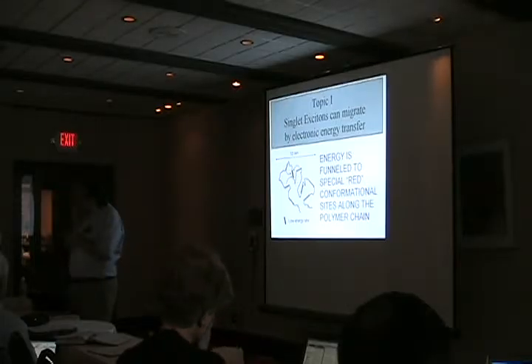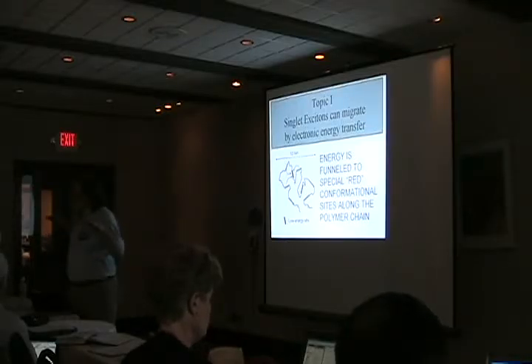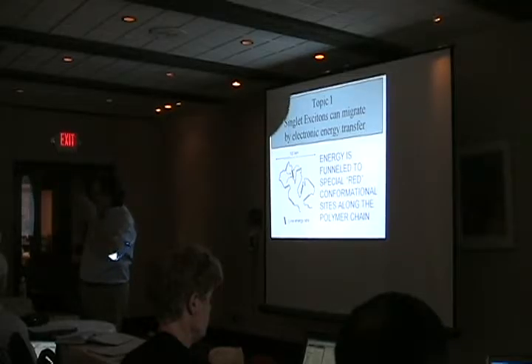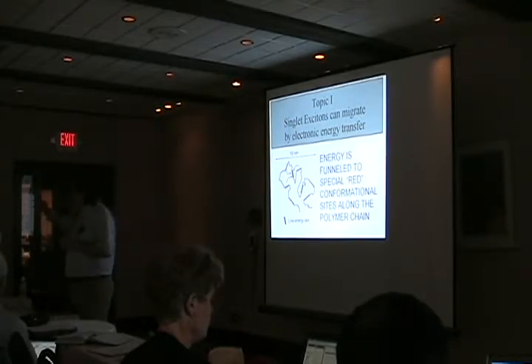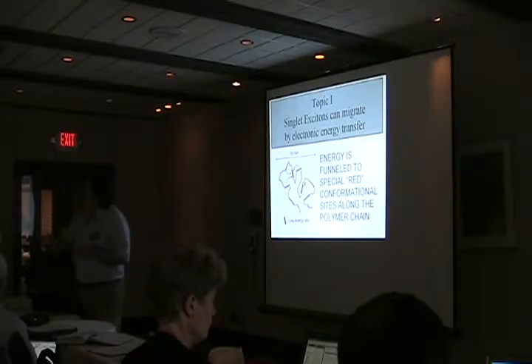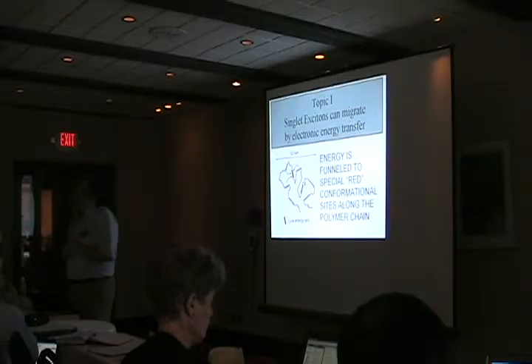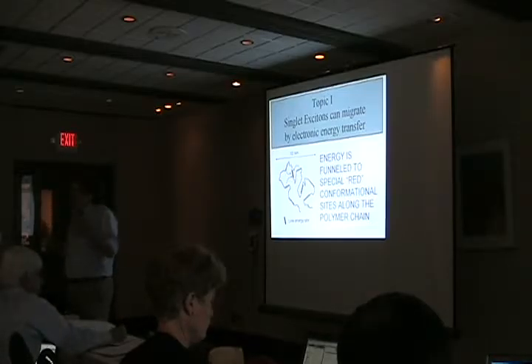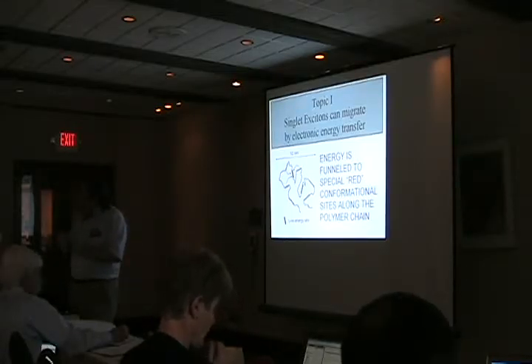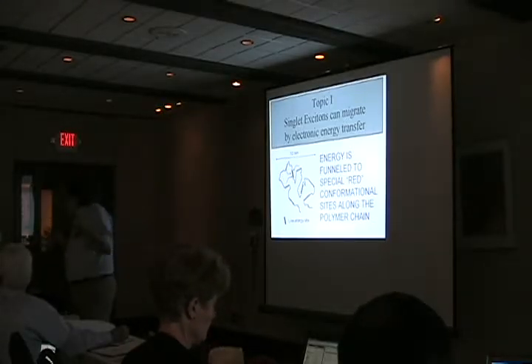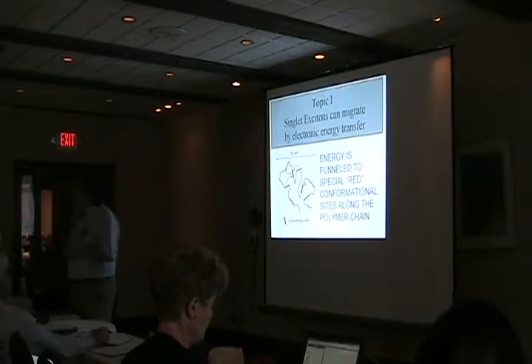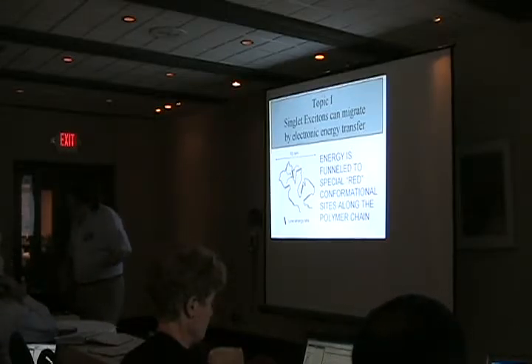If you took this chain and cut it into chromophores and put them isolated in a clean environment with no impurities, they'd all have about the same energy. Not high resolution. You know, if you did it with high resolution, they'd have different energy. And energy would slowly transfer between them, very slowly, just stuck because of having almost the same energy. What you want is to have one of them have lower energy so there's greater overlap. And what happens is the polymer self-assembles. It goes into a conformation that produces, it turns out, a Poisson number, because there's a small number of them, of low energy sites. And the energy hops from anywhere in the chain effectively to that low energy site. Now, of course, if you had 20 of them, you would be thinking less about Poisson, but it turns out there's often 0 or 1.